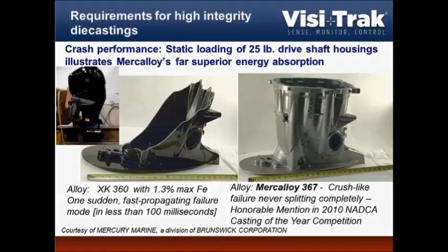So traditionally, high iron, their so-called XK360 alloy was used, and they could just barely pass a 30 miles per hour log test. And by developing and then switching to their proprietary Mercalloy 367 in this case, they actually managed to save this casting beyond the log test. It did not split completely, not break completely, and this is actually now after a 60 miles per hour log test. So a huge improvement in terms of crash performance.